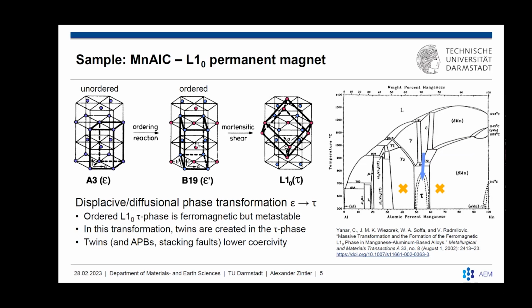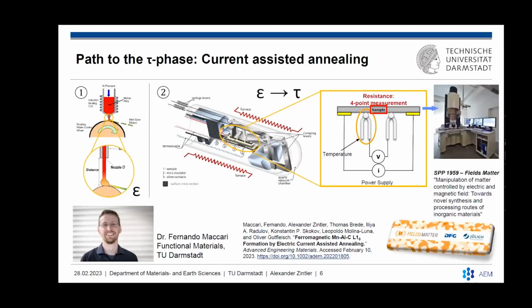But Fernando Macari, who is also a researcher here at the TU Darmstadt, and he should be present, I think, in the room upstairs. I'm not sure if he was able to make it. Basically, he cooled or quenched the melt in this process here to the epsilon phase. And then after that, he used current assisted annealing to get the material system from the epsilon to the tau phase. So in this current assisted annealing step, it's possible to control the annealing procedure very carefully.